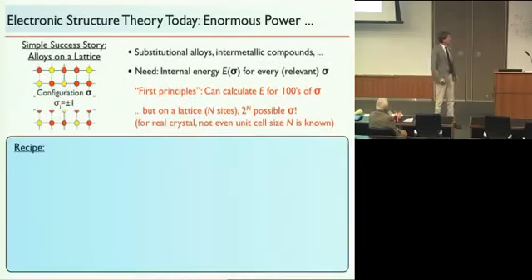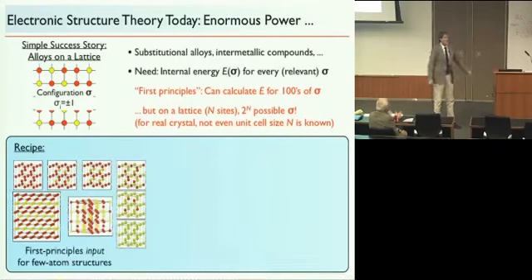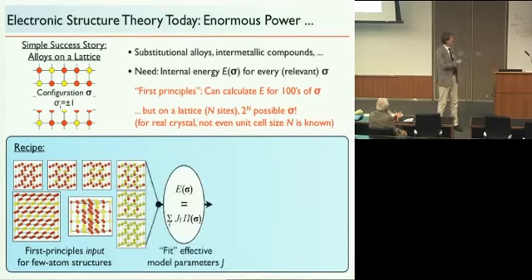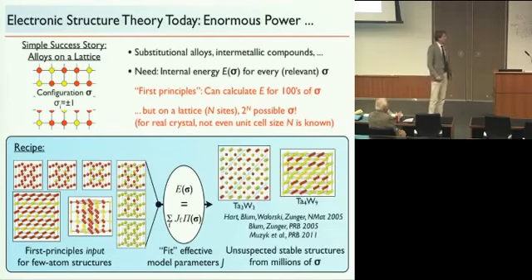You could, as a recipe, for instance, simply calculate the total energies of, say, a few hundred of these structures, then throw them into the Hamiltonian, the expression that I just showed you. This is a reduced form of that, but the J's are here again, and you fit the effective model parameters J. This connects back to the last new faculty lecture, actually, because compressive sensing, which Galen Reeves talked about, is the latest thing to do this effectively and obtain reduced models of this kind. Once you do this, you find stable structures for relatively simple alloy systems like tantalum tungsten, for instance, that look interesting, but they look nowhere as simple as those that we put in. And these are also not structures I, at least, would have first guessed as the stable structures, yet they come out. Now, this is work done about 10 years ago.